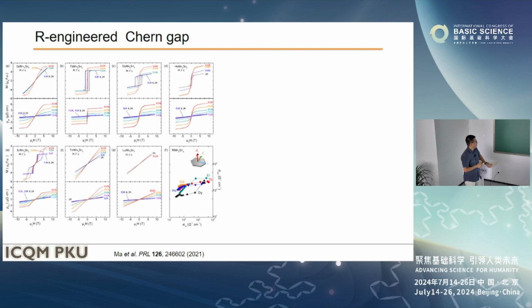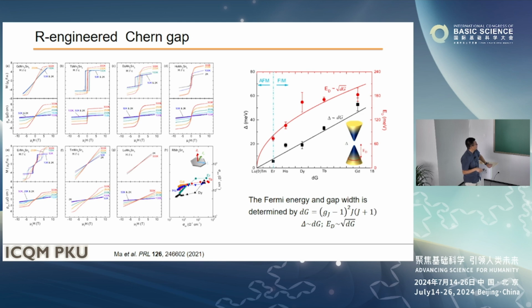Okay, we also did some measurements on other rare earth compounds and found that for heavier rare earths, you actually just close the Chern gap. And this gap closing can be understood if you introduce some de Gennes factor, and this one has a different compound and different magnetic ground state. For example, the terbium one is antiferromagnetic, but if you apply a field, it can be polarized to ferro. At the same time, you see a spontaneous anomalous Hall effect, which is consistent with our expectation. Okay, I don't want to introduce this too much.